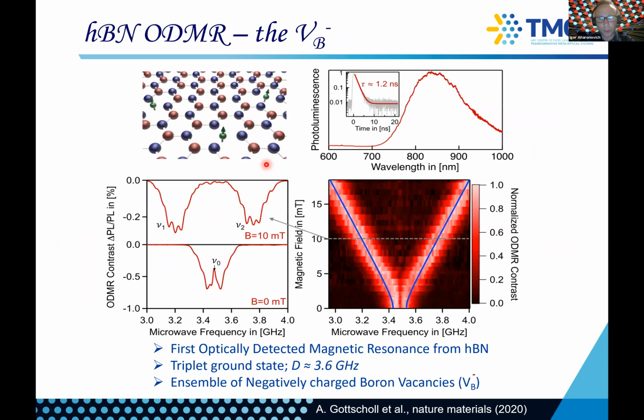So what we wanted ideally to find is a system that would exhibit basically an NV type ODMR with a large ground state splitting. And we found that after ion irradiations, these emissions show a very large broadband emission at around 800. You may remember, you would actually have seen it when I showed you the silicon and oxygen implantation at this range. It was actually formed just because it was an ion hitting hBN.